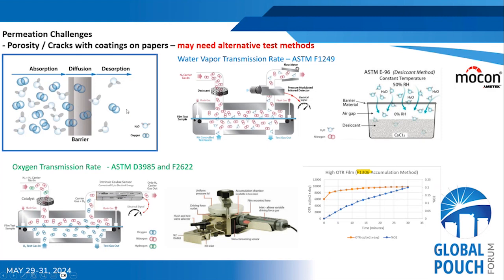The way we test the sample is we put this material into a diffusion cell. That's what this blue line here is in this water vapor method, ASTM F1249. On one side, we challenge it with a test gas, in this case water vapor, at a controlled humidity. To measure how much water permeates through it, we sweep a dry nitrogen gas on the other side. Any water vapor that transmits through is picked up by that nitrogen carrier gas, brought to a detector, and quantified. This method, ASTM F1249, and there are other international standards based on it as well, has been around forever, and it works great for polymer samples.